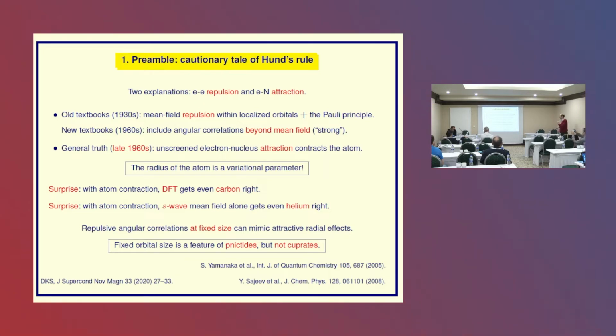And this has a direct repercussion for the high-TC superconductors, because in the pnictides, the iron T2G orbitals are caged in the tetrahedra, which are set up by the E2G orbitals, and this means that they behave like in an atom of fixed size. So the Slater's generally incorrect explanation of strong correlations is correct for the pnictides, because the size of the orbital is fixed by a stronger scale, by the binding scale.